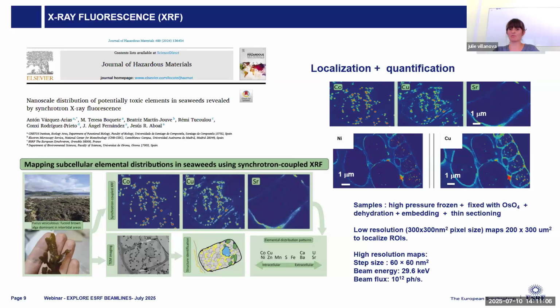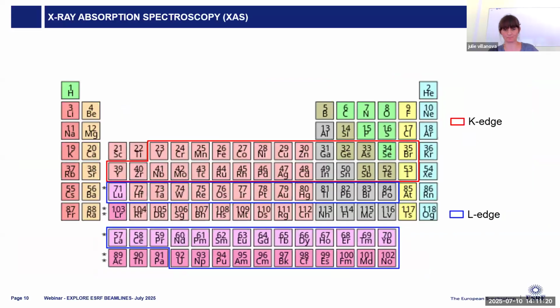And what is important to note is that thanks to the high flux and fast acquisition, we are able to have a kind of statistical study, meaning that we are really looking at a trend and not only looking at one map. Coupled with the fluorescence, we can look at, for example, the oxidation state of the chemical element we localized by performing XANES measurements. At the beamline, it's possible to access from the vanadium to bromine and then from yttrium to iodine K edge, and also some L edges.